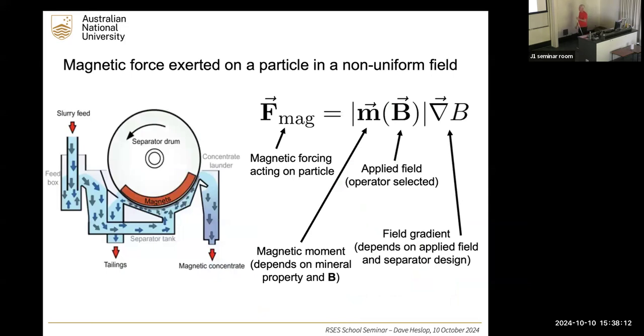So if we allow myself one equation, if we look at what's controlling this, the attractive force acting on a particle from the magnet is a combination of what's called the magnetic moment. That's just really how magnetic the particle is. That in turn is a function of how strong the applied magnetic field is. So that's a fundamental property of a given particle. And the force is also dependent on the field gradient within the separator. If the magnetic field was uniform, there wouldn't be any attractive force at all. So you need a non-uniform magnetic field, which is just represented here.